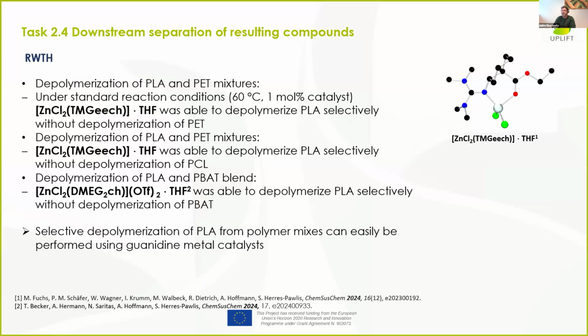As well, not only after the enzymatic process, but also after the chemical process, we found out that, for example, PLA, which unluckily is a bit recalcitrant to the enzymatic approach, was eventually well depolymerized, selectively depolymerized, by the guanidine catalyst from Hoffmann group. Specifically, they were able to selectively depolymerize PLA out of different mixtures, where, for example, PET was present, or PCL was present, or PBAT too.